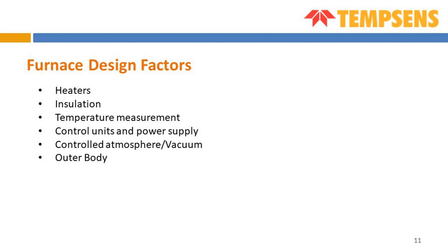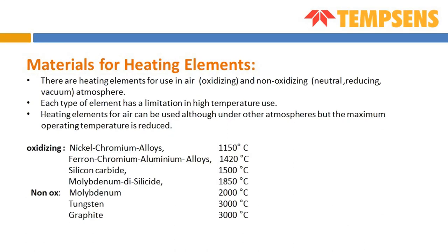As I said, there are different types of heating elements available, based on the temperature and the atmosphere. Nickel chromium alloy can go up to 1100-1150 degrees centigrade. Silicon carbide we use when your temperature is about 1500 to 1550 degrees centigrade. Molybdenum disilicide, MoSi2, we use up to 1800 degrees centigrade. For vacuum or non-oxidizing atmosphere, we use tungsten, molybdenum, or graphite heaters. That is for vacuum furnaces, where we can use that type of heater at much higher temperatures, approximately up to 3000 degrees centigrade.